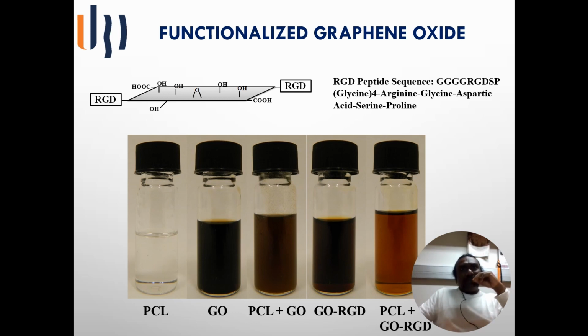by using some chemistry, and you can see here the solubility of RGD peptide functionalized graphene oxide. Here it is PCL in chloroform, graphene oxide in chloroform, and PCL plus graphene oxide in chloroform, and this is GO-RGD, and the next is PCL plus GO-RGD. You can see the clarity of the solution of PCL and the graphene oxide. So this little functionality of graphene oxide improves its solution processability a lot.